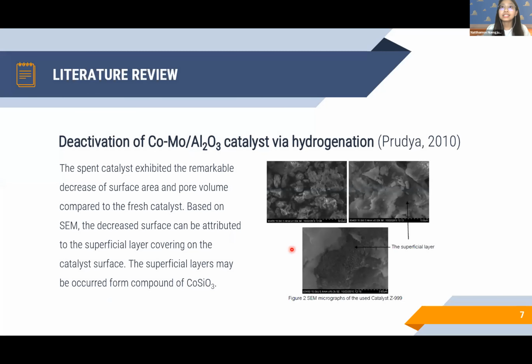The last one is research studying the deactivation of the commercial hydrogenation catalyst Z-999. The spent catalyst exhibits a remarkable decrease of the surface area and pore volume compared to the fresh catalyst. The decreased surface area can be attributed to the sulfur superficial layer covering the catalyst surface.